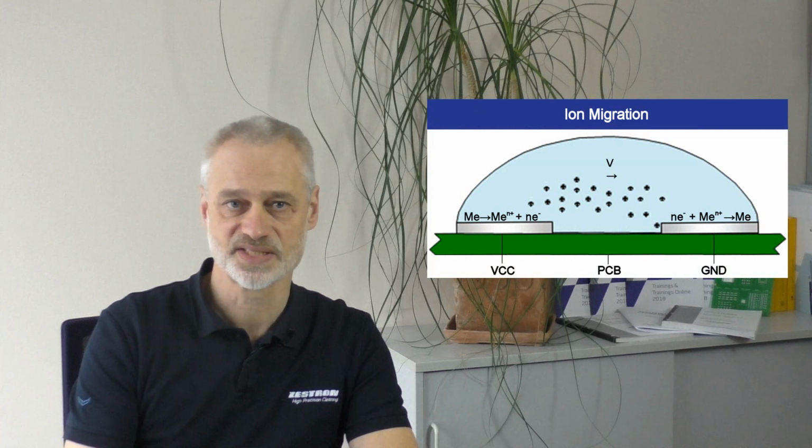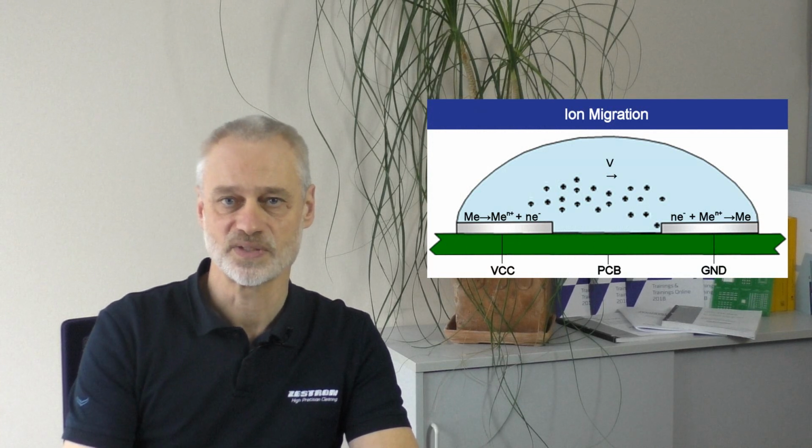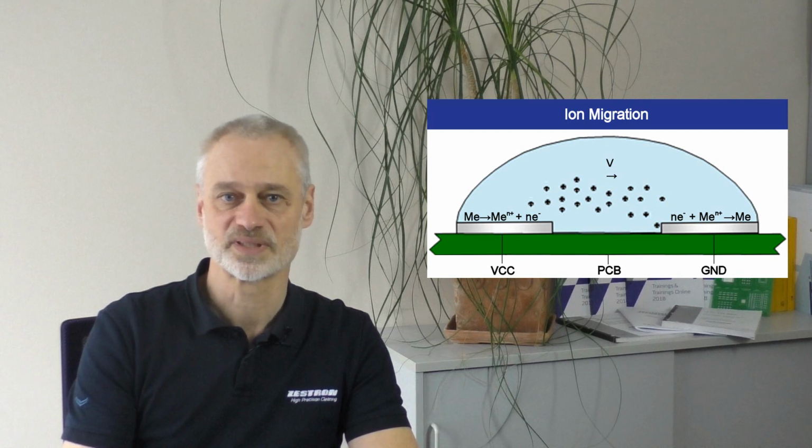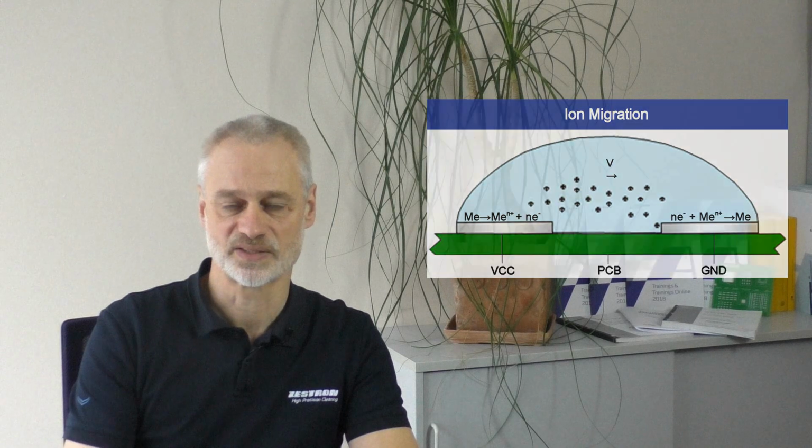The second step is the ion migration, determined by the concentration of the ions, in this case the hydroxostannates. They spread out to those areas where you have an alkaline condition in the water, respectively condensation layer. So the dendrite grows along the concentration gradient, which means that it grows independently from the electrical field along the alkaline areas.